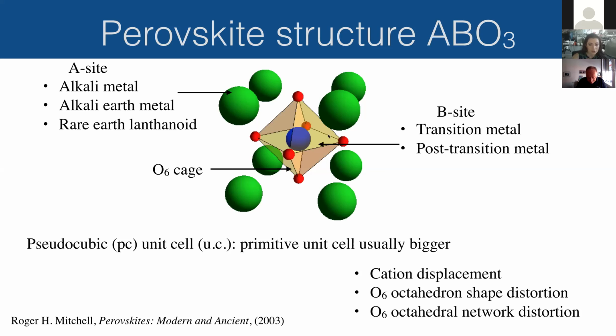And in 3 dimensions, this octahedron will be connected to another one right beside it, above it, below it, and in front and behind it. So it's a corner connected network of oxygen octahedra. So when you substitute different A and B site cations onto this type of perovskite unit cell, what you get is different distortions. So this means that what is shown here is what we call the pseudo-cubic unit cell, where you just simply think of the repeating unit of the structure as being a cube going between the centers of these A sites.